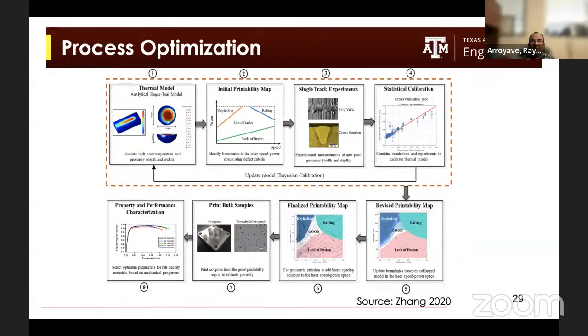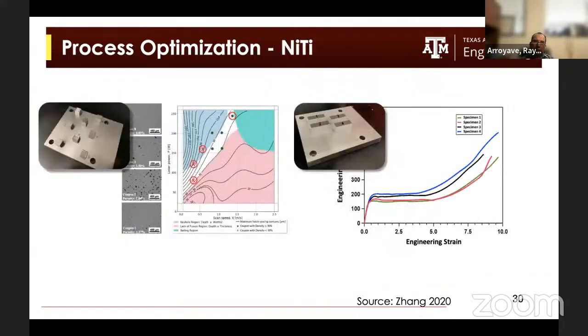And what we have found is that as long as we print things in regions that are not conducive to these microscopic defects, the properties that we get out of these materials tend to be very uniform, right? And that makes sense, right? We want the material to be not limited by the presence of microscopic defects such as porosity, right?